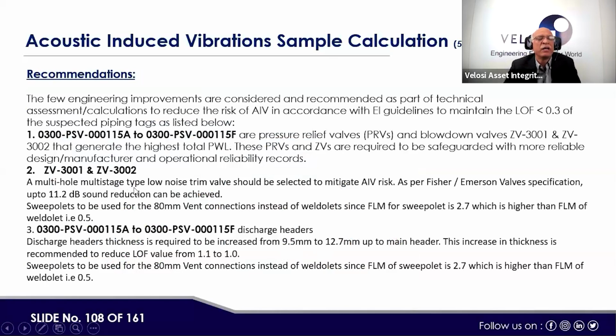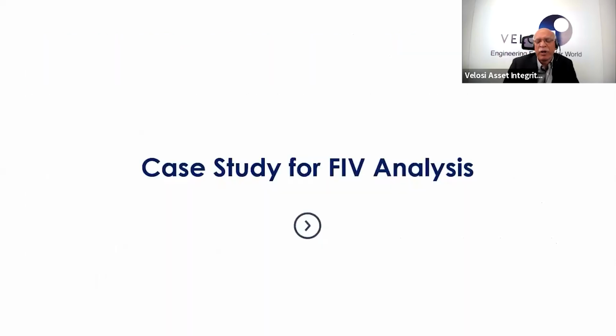A multi-hole, multi-stage low noise trim valve should be selected to mitigate AIV risk as per Fisher Emerson valve specification. Up to 11.2 dB sound reduction can be achieved. A swepolet is to be used for the 80mm vent connections instead of weldolet, since the FLM for swepolet is 2.7, which is higher than the FLM of weldolet, which is 0.5. Discharge header thickness is required to be increased from 9.5 mm to 12.7 mm up to the main header. This increase is recommended to reduce the LOF value from 1.1 to 1. So this is the recommendation, and then we prepared the report and submitted it.